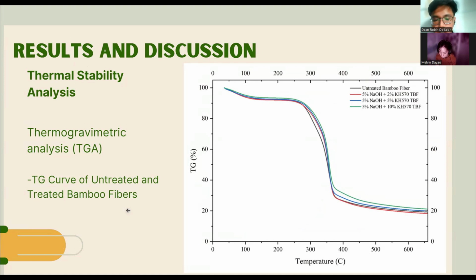loss percentage. In the higher temperature range, about 250 to 390 degrees Celsius, there was significant weight loss for all samples, with the untreated sample showing the highest weight loss at 64.30 percent by weight, followed by the fibers treated with 5% NaOH + 2% KH570, 5% NaOH + 5% KH570, and 5% NaOH + 10% KH570, with the latter exhibiting the lowest weight loss at 59.99 weight percent. This pattern suggests that fibers treated with 5% NaOH and 10% KH570 enhanced thermal stability among the samples, as it retained more mass during thermal degradation.